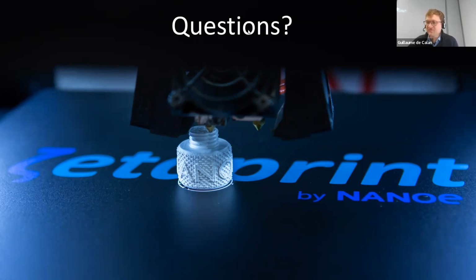So there are a few things here. To give you an example, let's say tomorrow I want to print this part. You just saw it in the webinar. This one has been sintered. It's a 5 centimeter part. I've never done it. I print it for the first time. Just use standard procedures, standard shrinkage, nothing modified. I could end up well with a plus minus 0.1. Usually that does, but I could also have surprises because the shrinkage doesn't happen as it is supposed to. There's a bit of deformation or something like that, in which case I might end up with a plus minus 0.2, 0.3. In the worst case, sometimes 0.5, that happens. Even on a part which is just a few centimeters. It does depend a bit on the shape of the part.